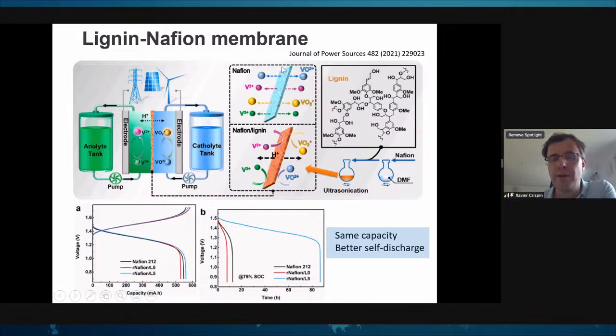So what people have done is to combine Nafion with lignin to prevent those vanadium ions from crossing the membrane, but still allow the protons to cross to do the electrochemical reaction at the electrode. And this has been working quite well. You can see here on the curve, the first one is a discharge curve, meaning that the introduction of lignin in the Nafion membrane didn't change the energy storage ability, but the retention and the ability to store the charge and to keep the charge stored has been improved a lot.